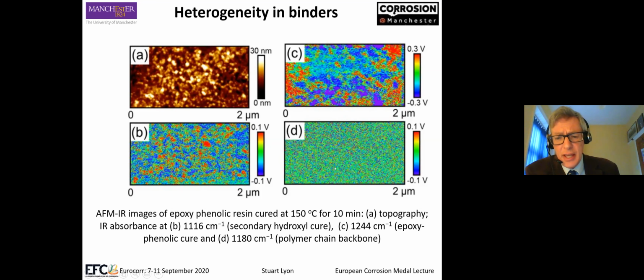And if we look at this here, just in case this was some kind of topographic artifact, this is the polymer chain backbone. This is the methylene wiggle in the polymer chain backbone, or one of those methylene wiggles, and we can see it's uniform. So if we look at the polymer backbone, it's uniform. If you look at the individual chemical functionality, it's different. And that was the first indication that these polymers were in fact chemically different at a heterogeneous scale.